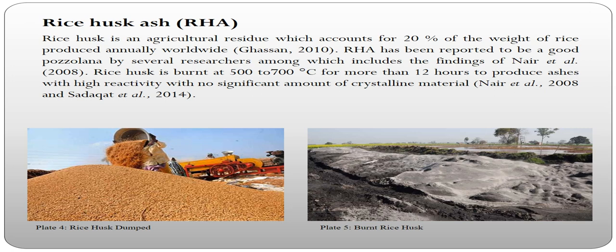Now, with this bulk production, bulk stock of rice husks is dumped on site, causing environmental pollution. Can't we think of assisting this farmer in utilizing this farm waste to earn more income? Look at, as shown in plate 5, rice husk has been burned, and as a result causing effect to our land, which is not even adequate for use for farm production. All the important organic matter, nutrients, and other things are being burned as a result of the heat during the burning of the rice husk. This is totally bad, and that is the reason why there's a need to encourage the use of this material in concrete so as to prevent this environmental pollution and destruction.